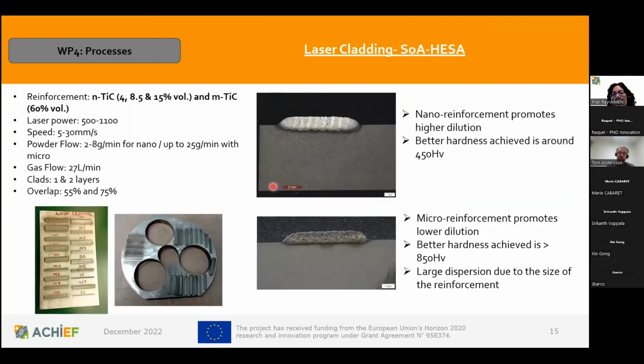With the cladding, we created some small batches and used different reinforcements, different types of particles, using titanium carbide as nano, but also as micro. We changed the laser power, the speed, the powder flow, and the gas flow in order to protect against oxidation, and different overlaps. With the micro reinforcement, we get better hardness, at least at room temperature, because with nano, we promote higher dilution. But the problem with micro is that we have a strong dispersion when we make this microhardness test, because of the different size of the reinforcement and the alloy.